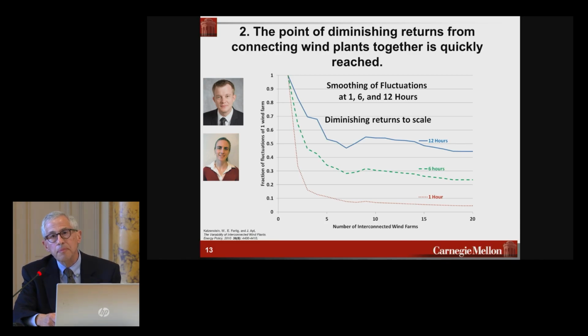So again, the top curve is the 12-hour, the strong fluctuations. The bottom curve is the smaller fluctuations, but important for the grid. And you smooth about 95% of that out. But that means that if you have a small scale, you can add just a few wind plants together and smooth much of that out if you're feeding, let's say, an electrolyzer or an ammonia plant.